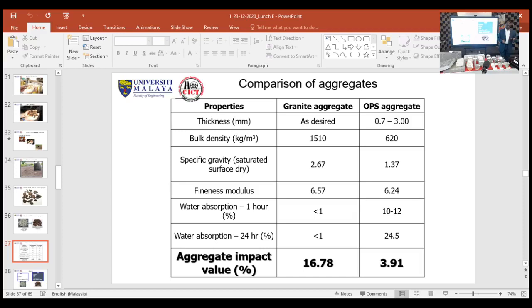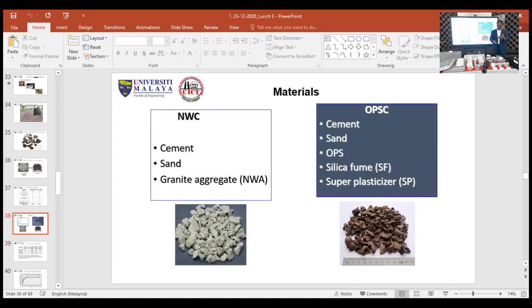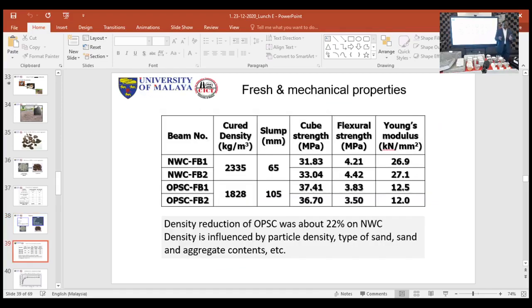So that's what enabled us to move forward to investigate this shell as a replacement for the conventional normal weight aggregate concrete. So we have utilized conventional normal weight aggregates in normal weight concrete. We have utilized oil palm shell in this. However, we used additional cementitious material, pozzolanic material, silica fume. I'll tell you the reason later. So the density you can see of the normal weight concrete is 2300, whereas for the lightweight oil palm shell concrete it's about 1800.